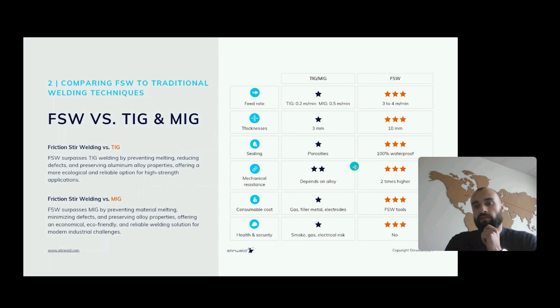Regarding the mechanical resistance, friction stir welding often provides twice higher properties if you look at the ultimate tensile strength of the material. The thing is, we are heating less than in TIG or MIG as we remain under the fusion point. So we keep the mechanical properties really close to the ones of the base metal.